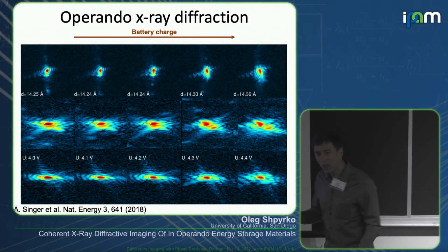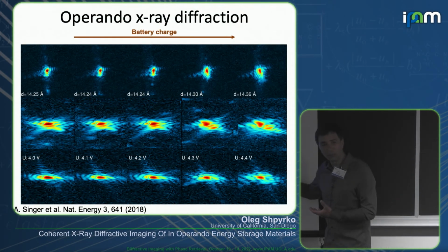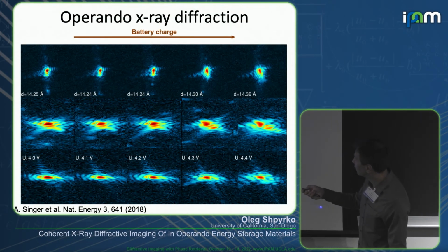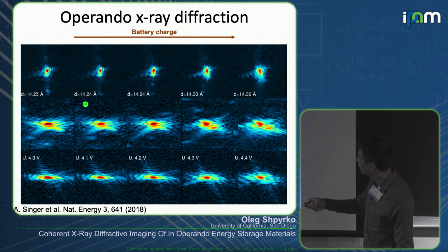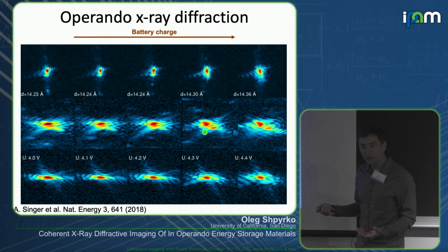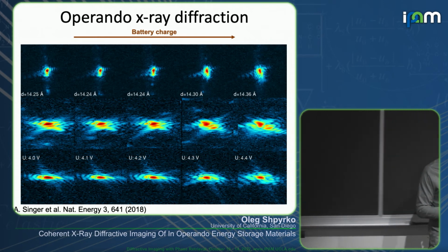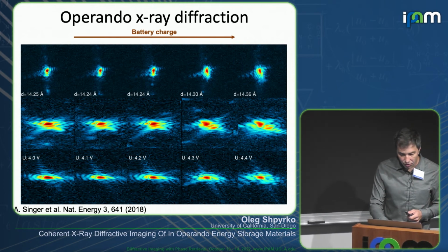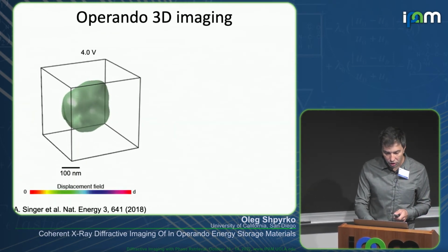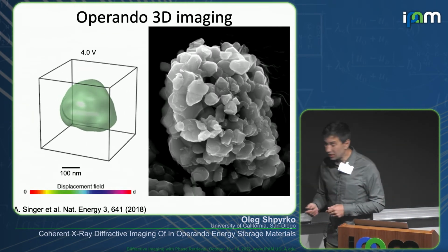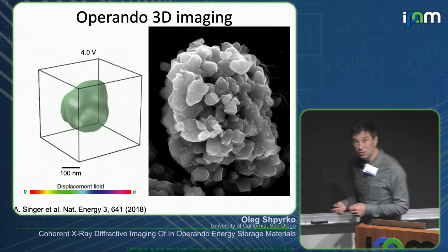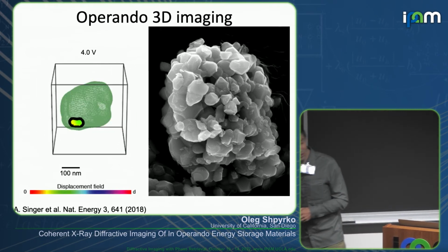People who train to see things in reciprocal space by looking at the diffraction patterns, as the voltage increases, some of you may actually figure out that as you're charging it, it becomes more and more defective, so to speak. There is more complexity in the diffraction patterns as you increase the voltage. But let me show you what the reconstruction shows, because my postdocs and students claim that they can see it, and I can maybe see it if I squint my eyes.